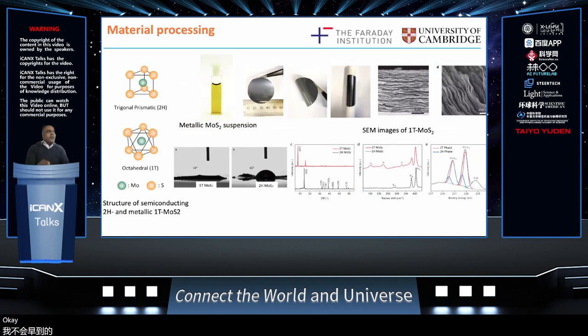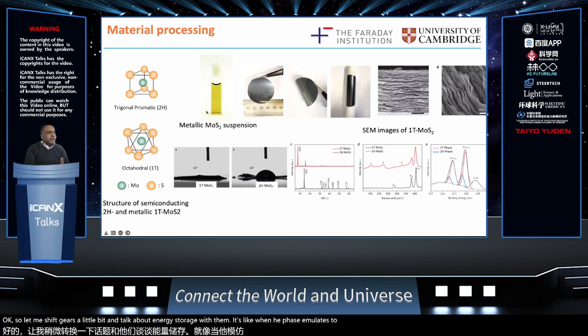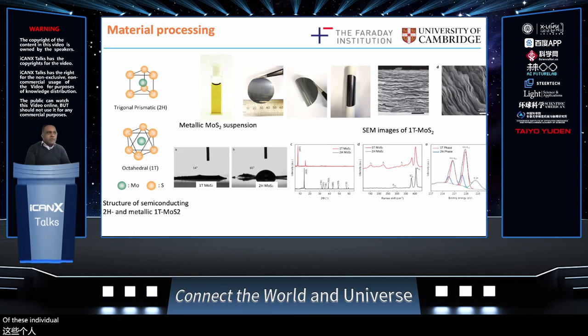Okay, so let me shift gears a little bit to talk about energy storage with metallic 1T phase MoS2. As I said, we do this butyllithium chemistry, and what we end up with is a colloidal suspension of these individual metallic phase MoS2 sheets floating around in liquid. We can use various techniques to then restack these nanosheets into electrodes. The simplest way of doing this is vacuum filtration, and then we end up with these beautiful electrodes that are flexible and easily handleable because they're quite robust.